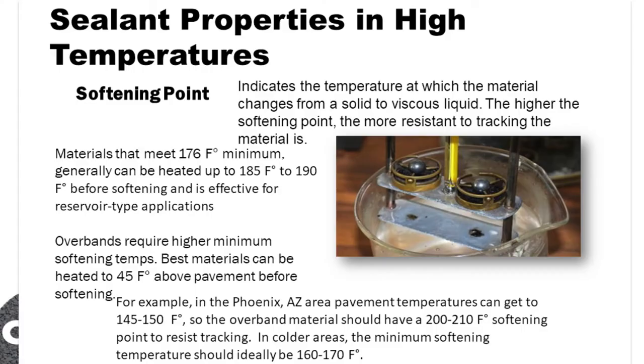Only sealants designed for ASTM materials get a bond test — it's part of the ASTM specification. The other test is the high temperature softening point. This is a ring and ball test where the tub below is filled with either glycerin or water. That brass ring is hollow at the bottom, they put a disc of sealant between it, then put a three-eighths ball on top of it. They submerge it into that water or glycerin, bring it up to temperature, and measure at what point that sealant gets so soft that the ball drops through it — and that's the softening point.